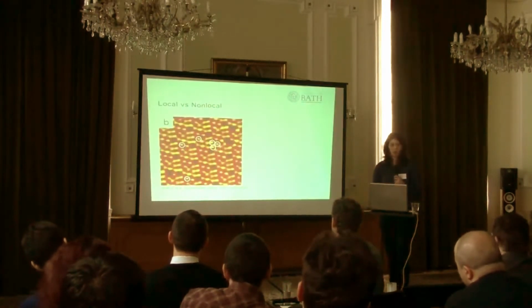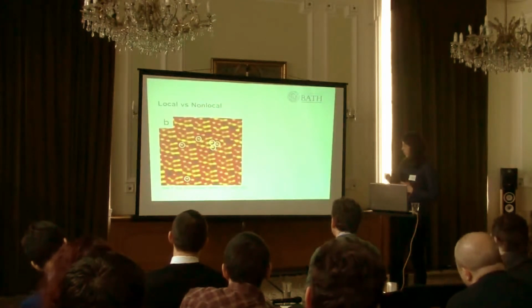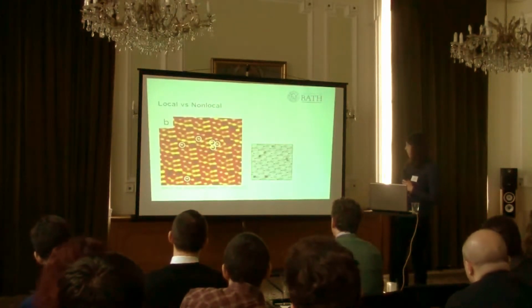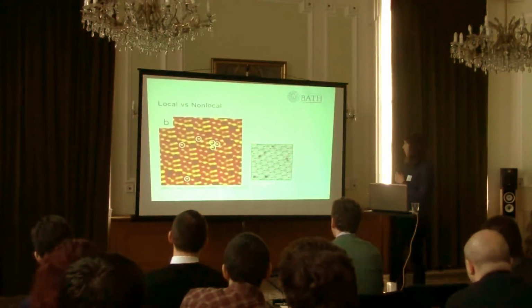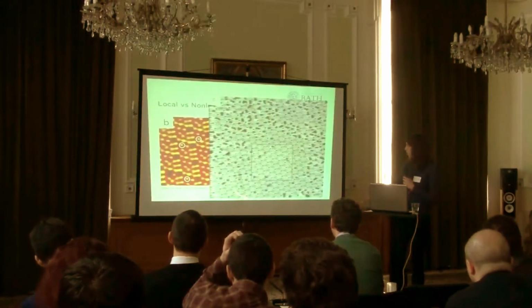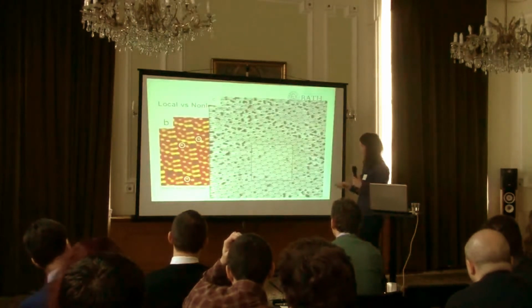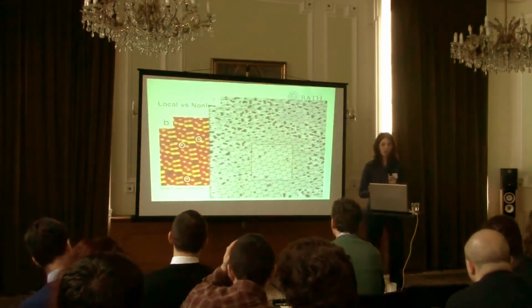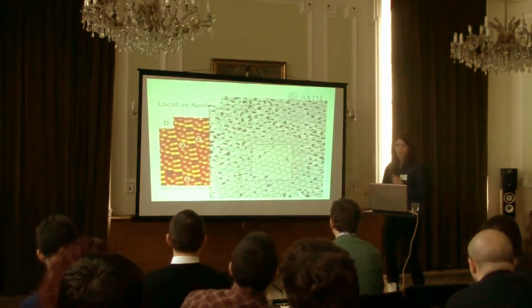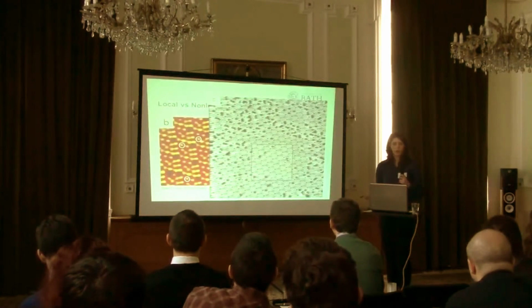they're going to dissolve. And what my supervisor noticed a few years ago was that if he did this experiment, so that's an image taken after he has done the experiment, all the molecules have left the surface. If you scan outside that area, you can see that quite a few other molecules have left the surface. And this is non-local, the so-called non-local atomic manipulation. Essentially, the tip has only been in this area here, but a lot of molecules over here have also been affected by what the electrons have done.